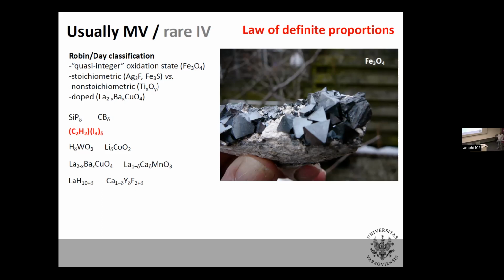And then finally, people have learned how to generate non-stoichiometric compounds using what's called doping, chemical doping. So that, for example, you can start with La2CuO4, and that's a black insulator. But if you substitute some lanthanum for barium, which is of course not isovalent, then you generate copper 3+, aside from predominant copper 2+. And that compound is not just metallic. If you chill it to sufficiently low temperature, you'll get a superconductor. A famous one, really. Nobel Prize worthy. If you think that a 3-element composition, lanthanum, copper, oxygen, with a slight substitution for barium, got these people a Nobel Prize, you'll think, gosh,